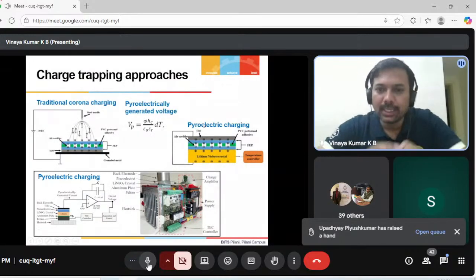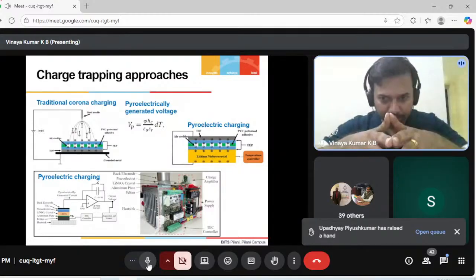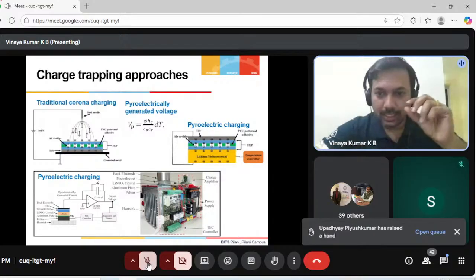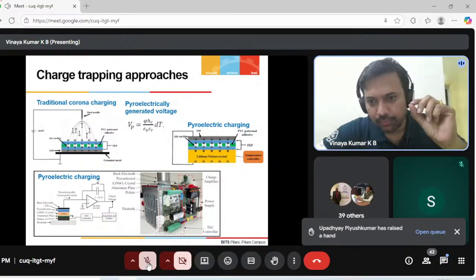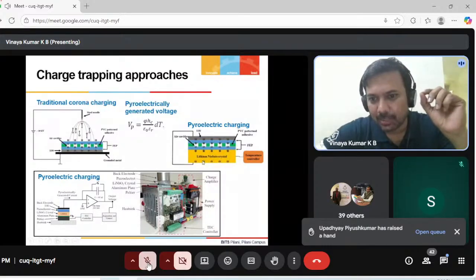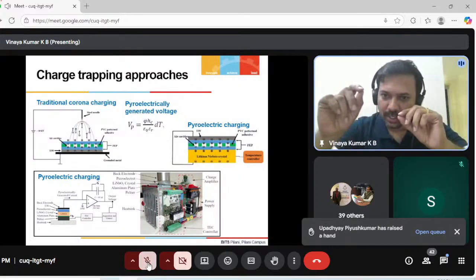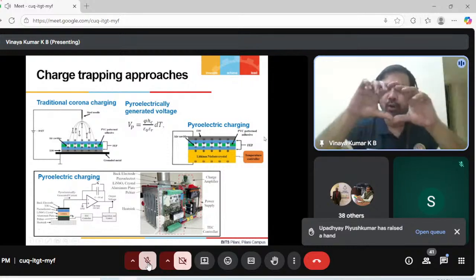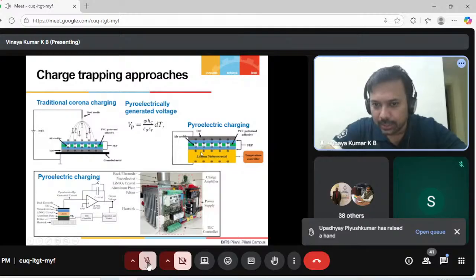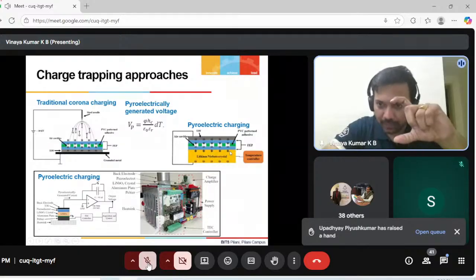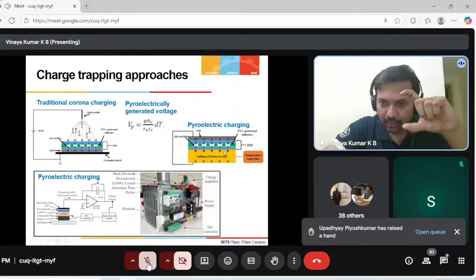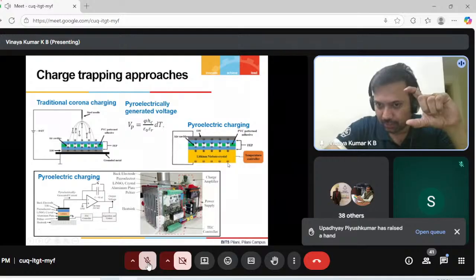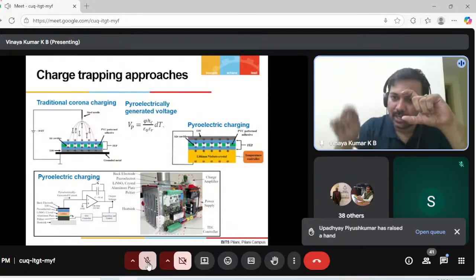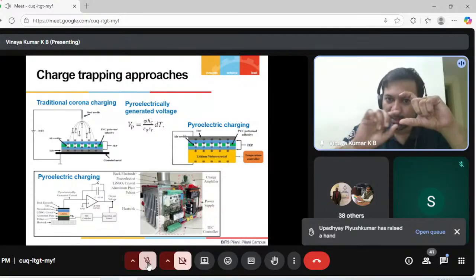Pyroelectric is basically wherever there is a change in temperature, right? Pyro is related to temperature, and the pyroelectric crystals we selected are lithium niobate and lithium tantalate. Whenever there is a change in temperature, they produce a very high potential on the polarized surfaces. As you can see, this is the pyroelectric crystal. I change the temperature on the positively polarized surface. It generates a very high electric field, a very high surface potential, and the other surface produces the opposite surface potential. So across the crystal, we generate a very high electric field just by changing the temperature.